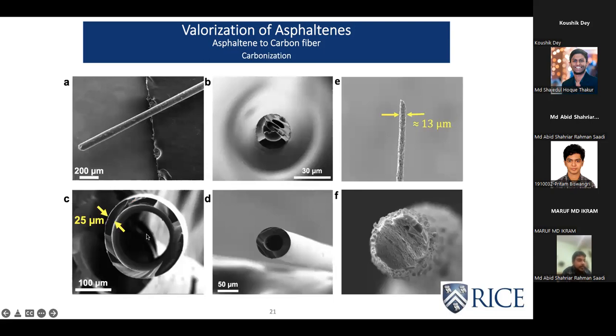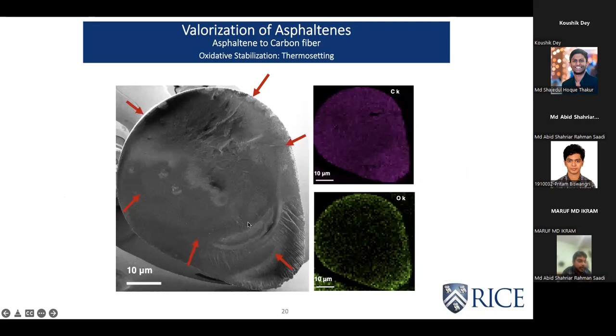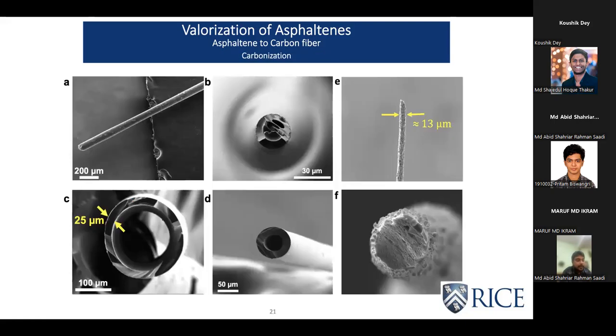These are some of the consequences: after carbonization, which was done around 600 to 800 degrees Celsius, oftentimes we found these hollow fibers. And this is a direct consequence of what we saw here. It happened because we were able to stabilize only the shell regions. The core regions were not cross-linked and therefore were not stabilized. As a result, during high temperature treatment, the core regions basically evaporated, and we ended up with hollow fibers.